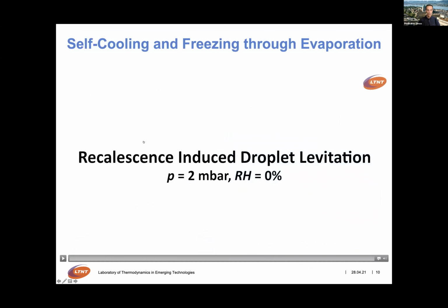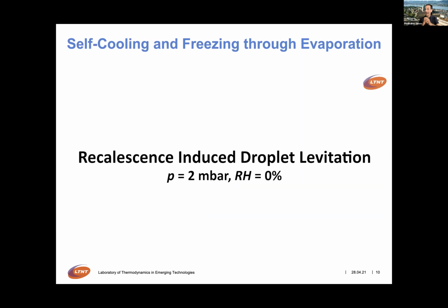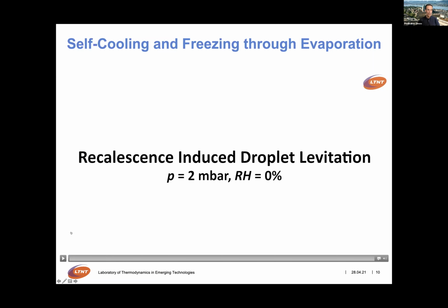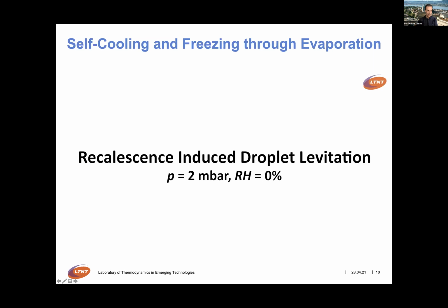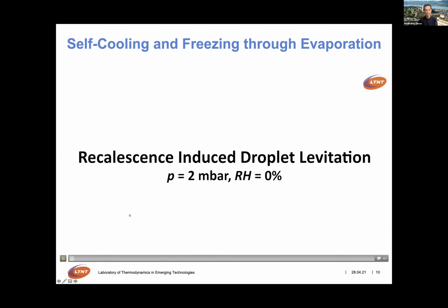Instead of telling you how we did it, I will show you an example of how this happens now on a nanoengineered surface of that kind. Only now our cooling does not occur through temperature, but through the fact that we have our droplet in a low pressure, dry environment. The droplet vaporizes, self-cools to minus 15, minus 20 degrees, although I'm not showing it here, and then suddenly this phenomenon takes place, and this vapor explosion takes place from all over the droplet, the top and the bottom, and we've designed the surface so the following occurs.